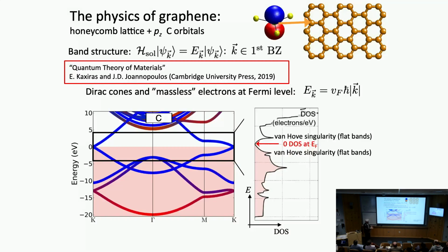The problem is that it's impossible to access these regions of diverging density of states, because if you look at this range of values here, this is in electron volts. These correspond to 2 or 3 electron volts away from the Fermi level. And it's very, very difficult, close to impossible, to access states that are several electron volts away from the Fermi level. And that's very important for what's coming next.